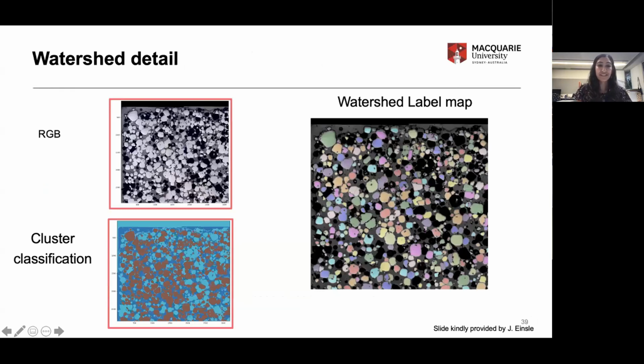So just to have a closer look at that red, green, blue color contrast, this is what we're exploiting here. All optical images will have these built in, and many SEMs and field emission SEMs actually now run on red, green, blue color channels. So that means that if you don't have a grayscale intensity image, you'll automatically get this cluster classification. And we only needed to train 5% of the pixels within that previous image that I showed you to be able to get a really good watershed label. This is continuing work in progress, and you can see that we've got a few blips we need to sort out, things like some over segmentation problems, but that will come from fine tuning those parameters.